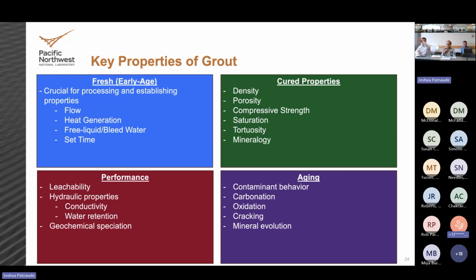Other performance parameters: the main one is how fast can water move through the material. If you make a very impermeable material, you get low water transport, low rate of water going in, low rate of other environmental species going in, and low rate of release. And then in terms of aging, again, depending on the application, if your disposal site presents a pathway to groundwater or back into the biosphere, we want to know the long-term performance of the material. Some processes we want to be evaluating in the laboratory, and developing models for how our contaminants behave over long time frames, are the rate of carbonation of our materials and the rate of oxidation, because those change the properties within the grout, depending on how you engineered it, for better or for worse.